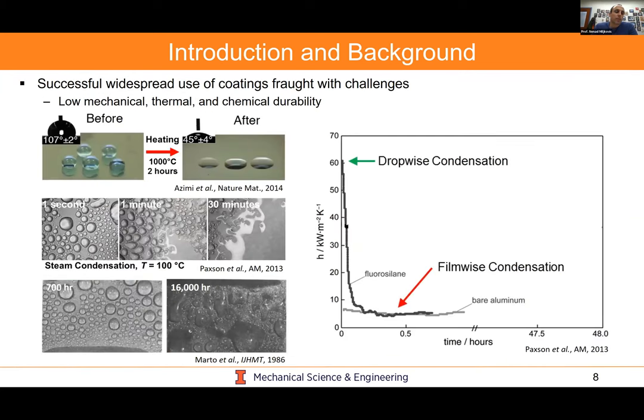So if we look at what typical dropwise condensation behavior is like on a common surface, like a self-assembled monolayer or a polymer film, what you'll typically see is you'll coat the surface very early on, within 1 second to 1 minute, and you'll see droplets. But then very quickly, within 30 minutes, you'll see film starting to form on the surface.